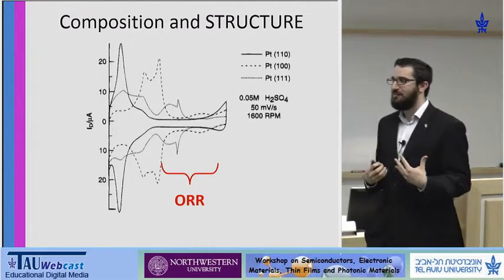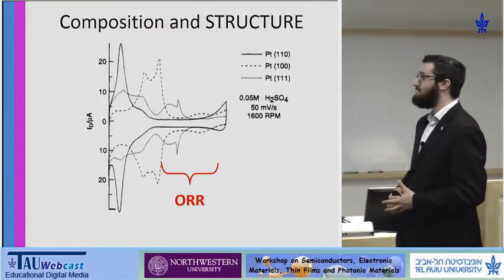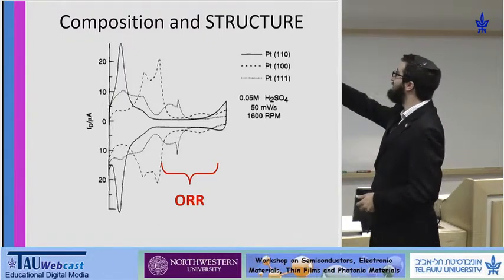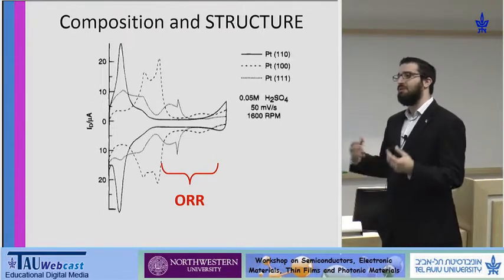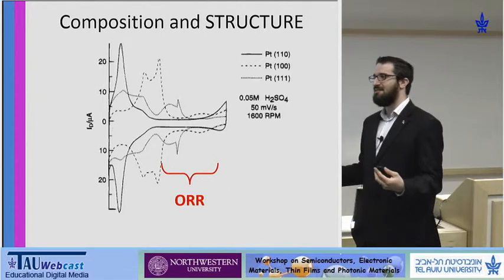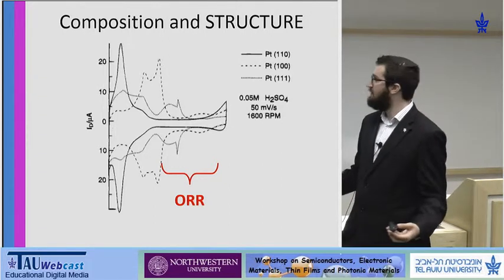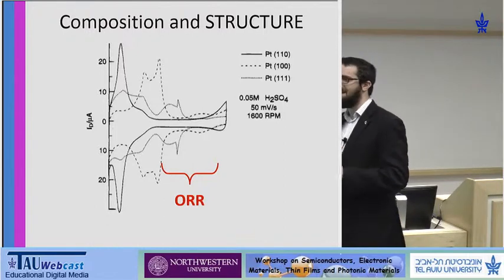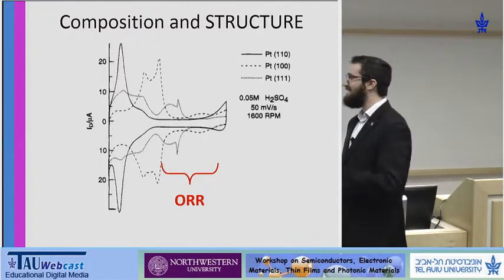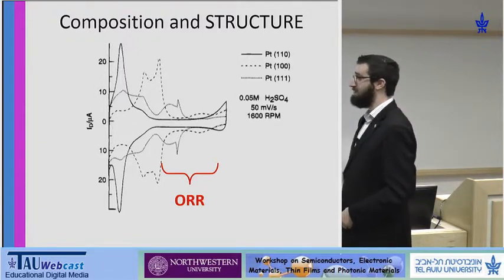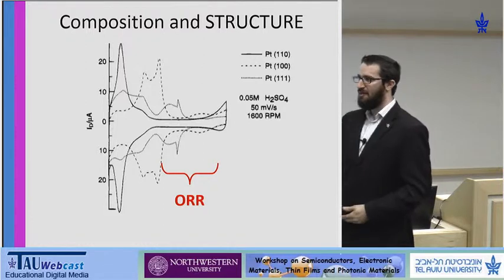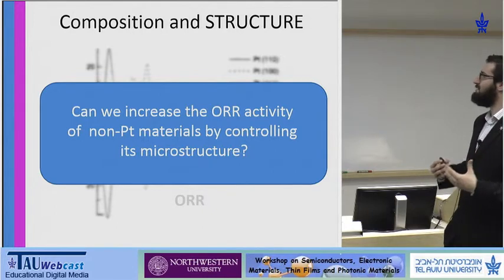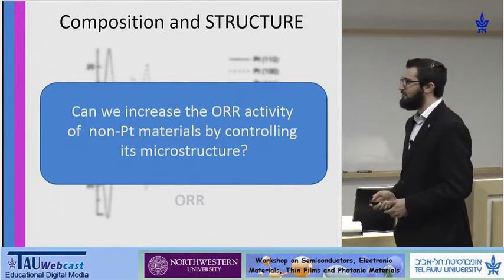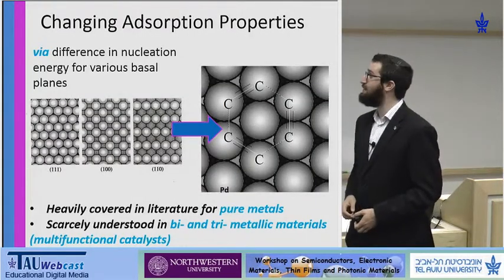Not only is platinum the most active, but different crystallographic orientations of platinum show different responses for oxygen reduction. So even though platinum is an extremely active catalyst, it's highly dependent on the crystallographic orientation. So what we want to do is take the same idea, this dependence on crystallographic orientation, or facet engineering, if you will, and apply it to less noble metals, even transition metals, in order to find the most active planes for oxygen reduction as a way of replacing the catalyst from platinum to other metals. So the key question is, can we increase oxygen reduction activity of non-platinum metals by controlling microstructure? And the answer is, we hope, yes.